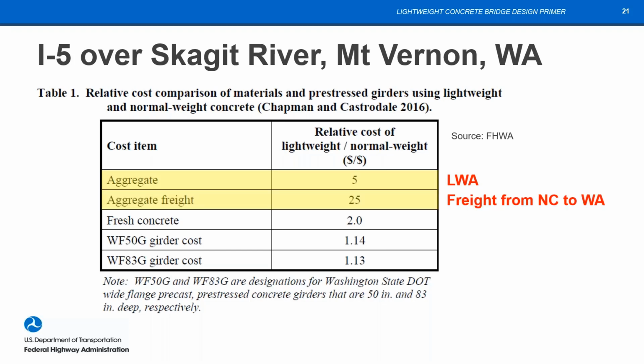The freight was 25 times the cost that they had for freight for the normal weight. And that's because it was being brought in some cases by truck, but typically by rail from North Carolina all the way to Tacoma, Washington. However, when you put all of that into the fresh concrete, the batch concrete was only 2 times more than the normal weight.